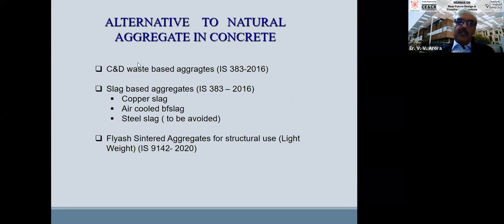I see alternatives to natural aggregates. C&D waste-based aggregates, we are now mentioning in 383. Then we have other alternate aggregates: slag-based aggregates, copper slag, air-cooled blast furnace slag, steel slag. Steel slag is to be avoided in RCC because it contains free lime. Now weathering plants are being put up to remove the free lime, but caution has to be taken with this steel slag. But air-cooled blast furnace slag and copper slag are very good materials. These two materials can be used.